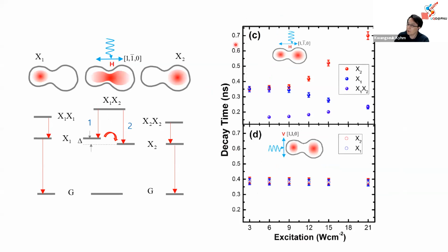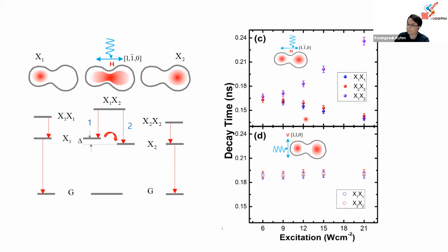So we plot the decay time versus excitation for the two excitons. The high energy decay time becomes fast, and the low energy one slows down. And the coupled biexciton increases. Okay. On the other hand, with the V-polarized excitation, there is no change. Okay. So H polarization is more efficient to control the dipole interaction.